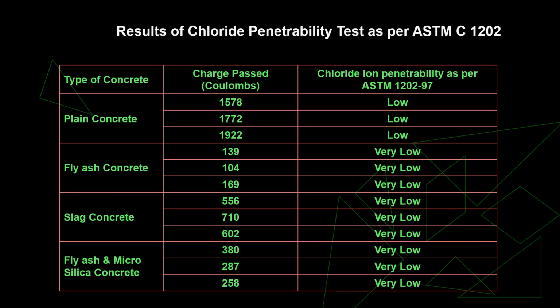Okay, now I want to show these results. All these concretes have been developed for M30 grade, and we got almost the same workability in all the cases. The plain concrete gave a higher number of coulombs. The fly ash concrete, made with 60% fly ash, gave very few coulombs. The slag concrete had 50% slag. So these are the numbers of coulombs. And this is a combination of fly ash and microsilica. So these concretes made with supplementary cementitious materials gave very low permeability. That means they are highly durable, and we are underestimating their capability by using the prescriptive parameters.